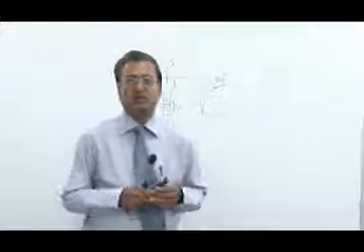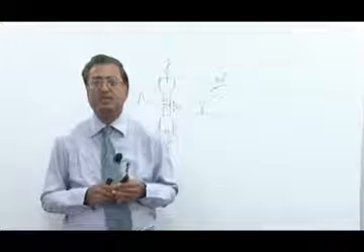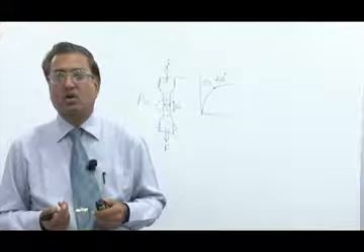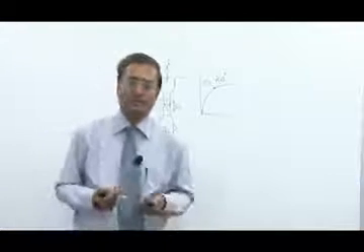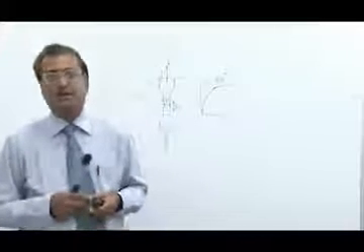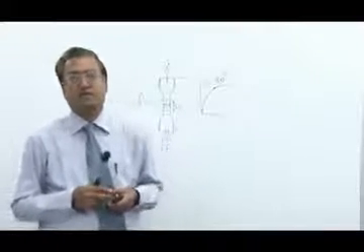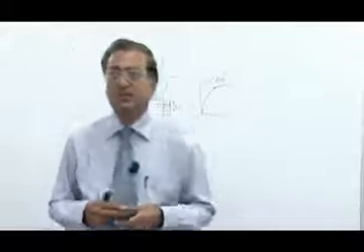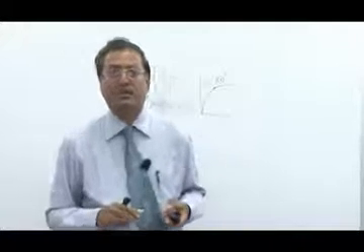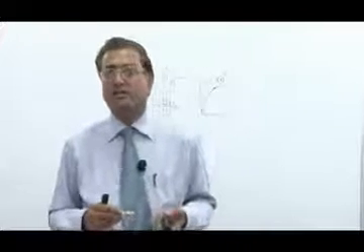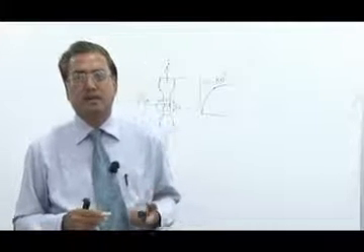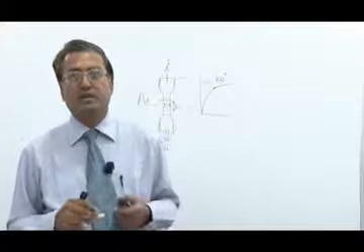One is called diffuse necking, similar to the tensile test, and it is followed by the second necking, which is called localized necking under the state of plane strain deformation. Diffuse necking provides a large extent of necking on the tensile specimen, similar to necking in a cylindrical specimen. Diffuse necking might terminate in fracture, but is normally followed by a localized necking.